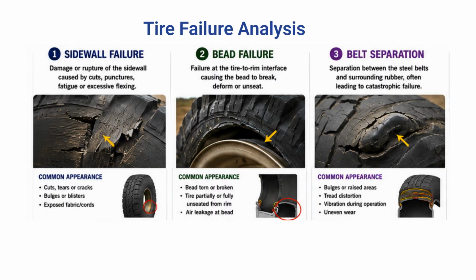Let us understand some major tyre failure modes and the visual signs that help engineers identify their likely causes. The first is sidewall failure, where cuts, punctures, fatigue, or excessive flexing damage the tyre's outer wall. Typical signs include cracks, tears, bulges, blisters, and exposed fabric or reinforcing cords. Common causes are sharp debris, underinflation, overloading, and impact damage during side slope or obstacle operation.